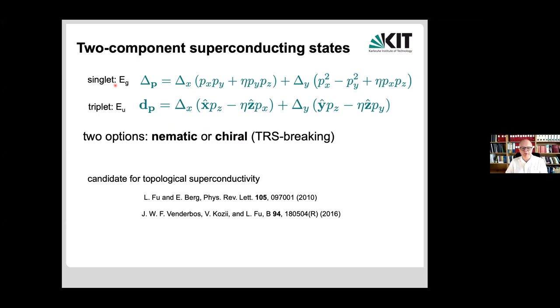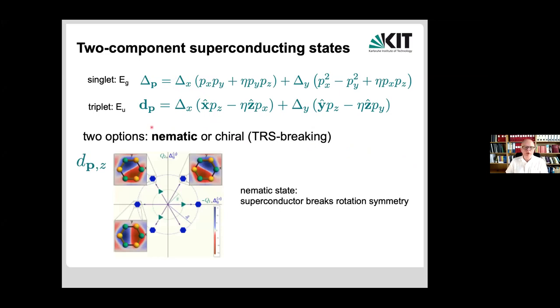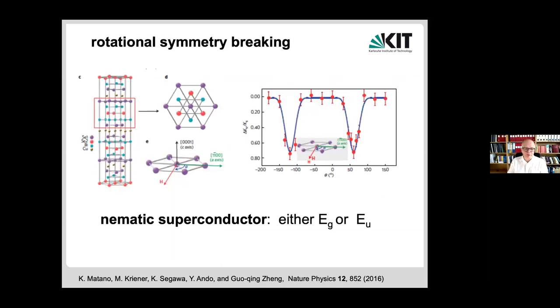Now, this analysis and classification was done in this very pioneering early work by Liang Fu and Erez, where they looked at the potential relevance for topological superconductivity in these systems. So what we looked at is what are the options for composite order in the specific system with a two-component order parameter. And clearly, if you look at, for example, the nematic state that will become relevant in a second, what you have is basically three degenerate solutions that are combinations of these two objects that are allowed near the phase transition as the relevant superpositions of the system. So you would then break a rotational symmetry in such a superconducting state, which is precisely what you see.